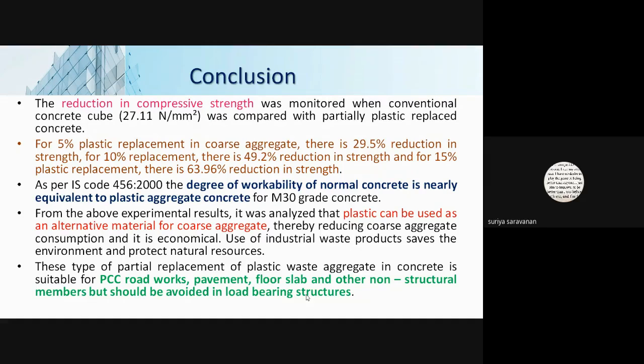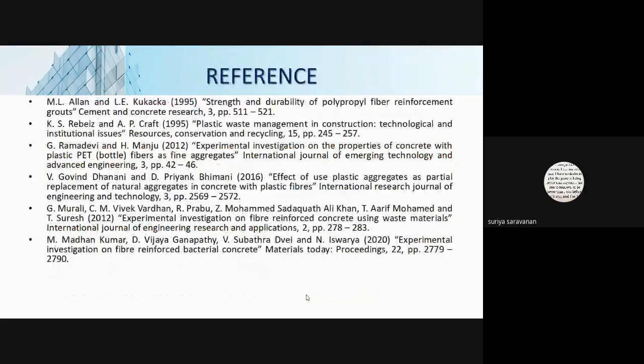If you take a building, 20 to 30% of the application of concrete is in non-load bearing structures. We can use this for filling and finishing. In such cases, we can use this plastic-based aggregate in the form of coarse aggregate. This type of partial replacement will be very well suited for PCC roadworks or pavement, floor slabs, and other non-structural members. But it should be avoided for any load-bearing structures. And these are the references we have seen here.